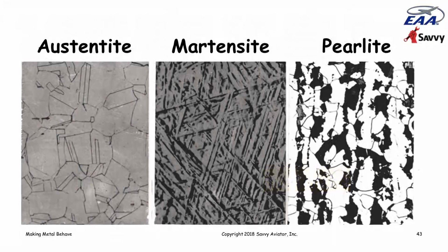And here are some metallographs of these three different states: the austenite, which only exists at very high temperature; the Martensite, which is the very, very hard, brittle form; and the pearlite, which is a mixture of iron and iron carbide. And you can kind of see what that looks like, and it's very soft. Now, the Martensite is what we get when we heat up steel into the austenite phase and then quench it very quickly. It's too hard and brittle to be particularly useful unless you happen to be making a knife blade.